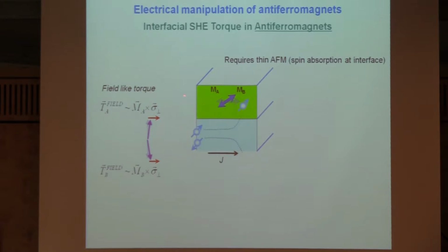Here you generate an effective field, an exchange field of your spin polarized carriers with the magnetization, which is typically oriented along the orientation of the incoming spin. So one can understand it intuitively that a spin enters your magnetic system, and then the exchange is so strong that you start precessing around the exchange interaction.